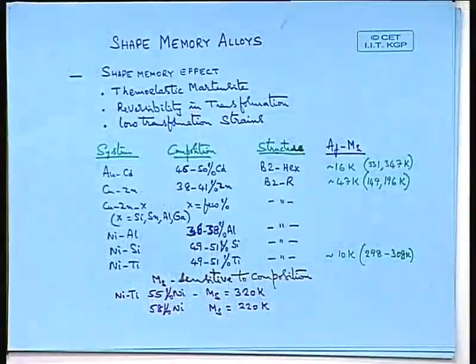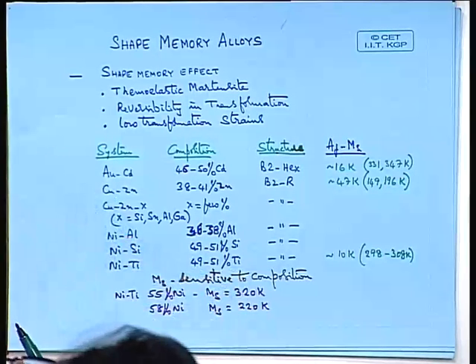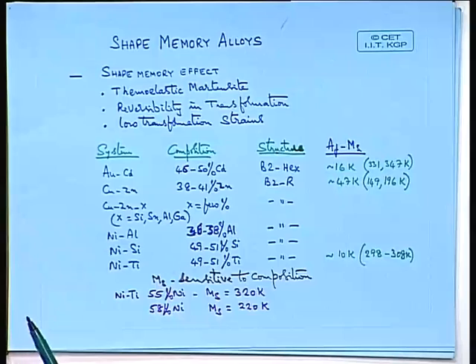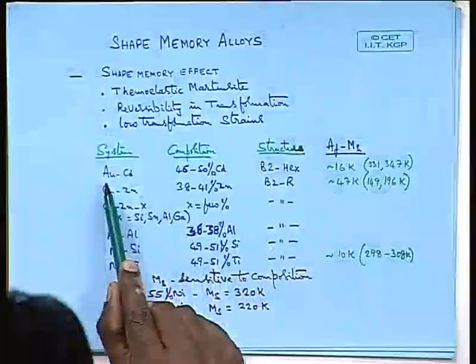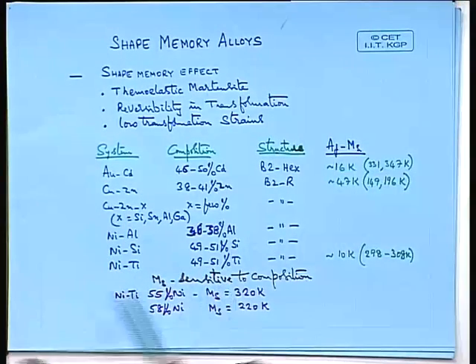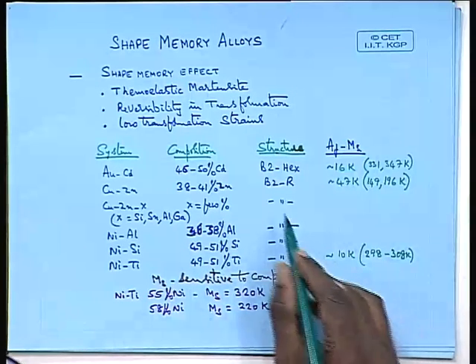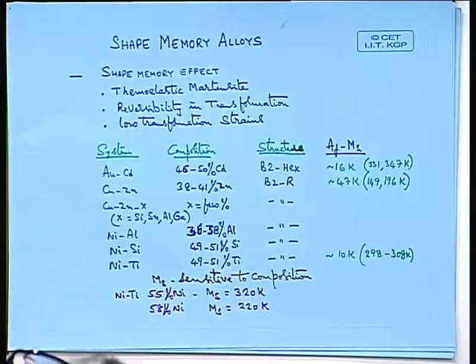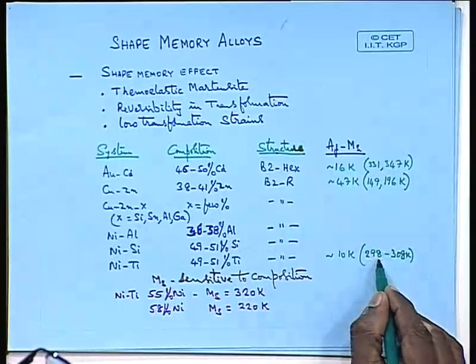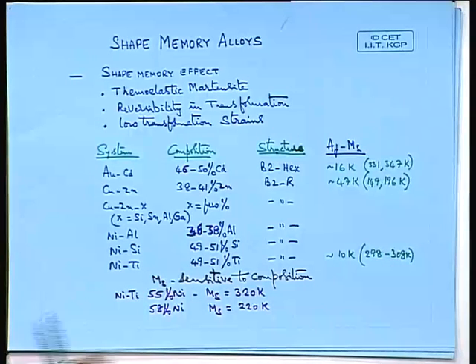Okay, so if you look at the various alloys which give you the shape memory effect, there are a range of alloys, mostly non-ferrous. Most of the ferrous type of alloys, iron nickel to some extent shows it, but as I told you, the difference in the temperature is too large for many practical applications. So you can see titanium nickel is one of the very crucial examples. The composition range I have given here is 49 to 51%, and the transformation is basically B2 to a rhombohedral type of structure, and the difference between these two temperatures is about 10 Kelvin. The MS temperature is about 298 and the AF temperature is about 308 Kelvin. So it's about just 10 degrees.